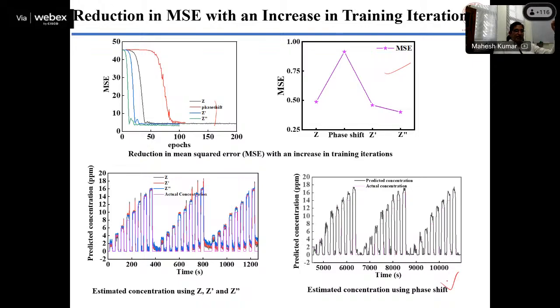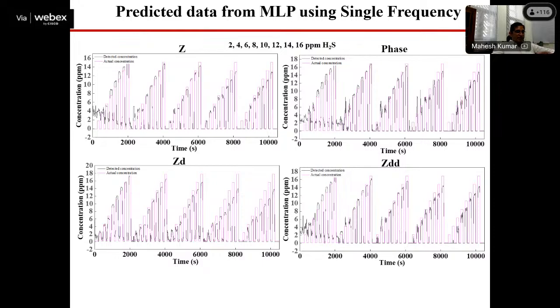Here we have used only a single frequency, around 10K, and then we predicted, and we are close to the actual values. Next, we used different models. First we considered only the single frequency. In the single frequency, the only problem is that in the first cycle we are not getting close, because there is a variation. The heater also takes some time to give a stable temperature, and we get some deviation in all parameters, either impedance, phase, or the real part and imaginary part.